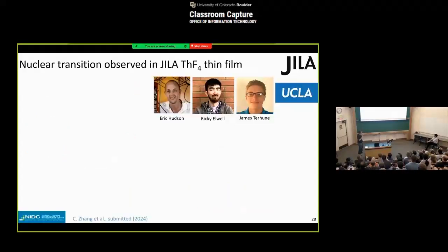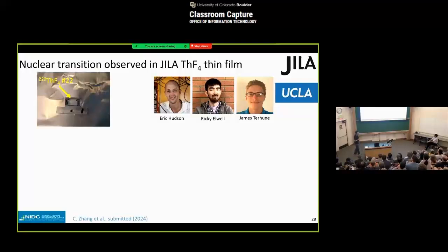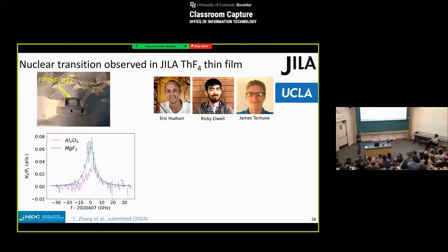with our frequency comb system. But we got very powerful friends at UCLA. You might know that Professor Eric Hudson was actually also a former CU physics grad student working at JILA. And so we sent over our thorium fluoride samples to UCLA. And here's one of the samples we sent over. This is our number 22 sample. So you can see that we failed more than 20 times before that. But now this sample actually worked.